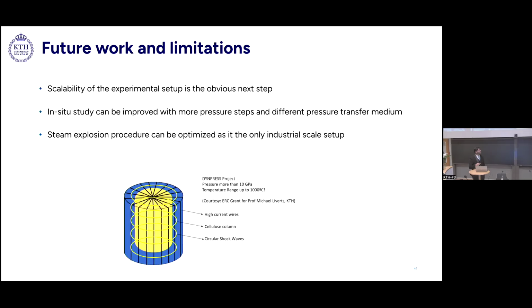We have a cellulose sample at the center of this tube, and upon exploding the high current wires, we will send circular shock waves inside the sample chamber, and it will treat the cellulose pulp at roughly 10 gigapascals of pressure and 1000 degrees Celsius. This entire phenomenon happens in literally nanoseconds, so we could get fibrillated cellulose in nanoseconds.